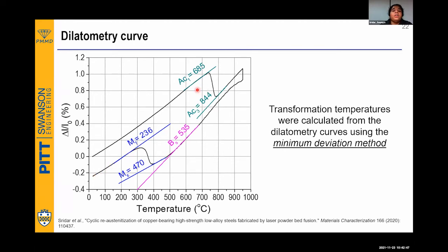So how are we going to measure this transformation temperature? It is called the minimum deviation technique. You draw a tangent, zoom in, and check the point from which the line starts to deviate from linearity. That is how you get the transformation temperatures. And these are all the important transformation temperatures for any steel.